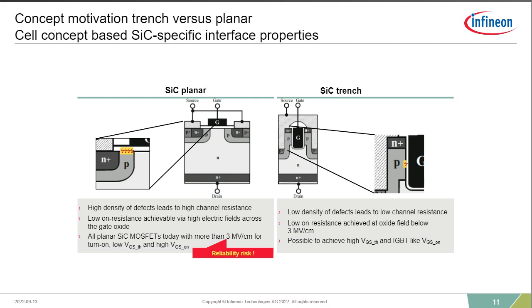So when we talk about those extrinsic defects that are in the base material, one of the things that becomes clear to you is in the construction of the devices. I showed before that there's a high number of defects that happen in the c-plane of a silicon carbide wafer material. And when you look at a DMOS-based device or a planar device, what you see is that the gate structure is really happening across this X-axis. Here you can see the P regions that are a critical area for dimension. So with the way that you construct a planar device, you tend to have the potential for a high number of defect density or issues in the area which is critical for the performance of the device, and that's this P region here. And when you talk about current flow inside of a DMOS device, you basically have a device that goes from the source area and then transitions down vertically. So you have this area where it becomes a critical dimension here in the x-axis for the construction of the device.